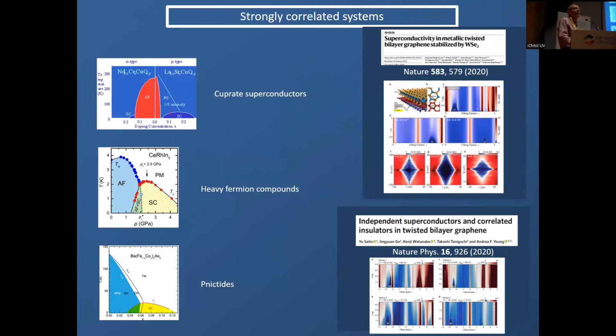twisted graphene layers is somehow related to the phase diagram of what is typically called strongly correlated systems, which were famous way back, like the superconducting cuprates, the heavy fermion compounds, the pnictides, and so on. All these systems show the coexistence of superconductivity and magnetic phases. It has been proven experimentally, actually, in the cuprates, that the superconductivity is not conventional at all.